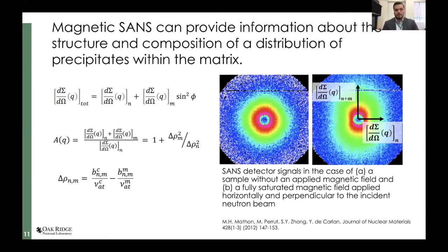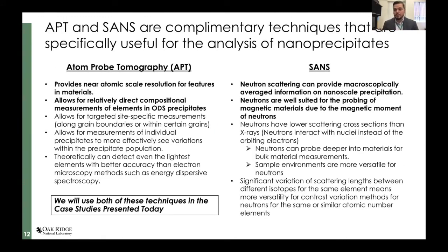We've also taken advantage of the magnetic nature of the iron matrix so we can deconvolute magnetic versus non-magnetic scattering media inside the iron matrix — using a ratio we call the A-ratio, which I'll use a little later. Not only do I enjoy small angle neutron scattering, but I'm also adept at atom probe tomography (APT), which is really good at looking at chemical segregation on the nanoscale. With SANS we can get a macroscale average of nanoscale features in the material, and then we can go in depth with APT and compare results.